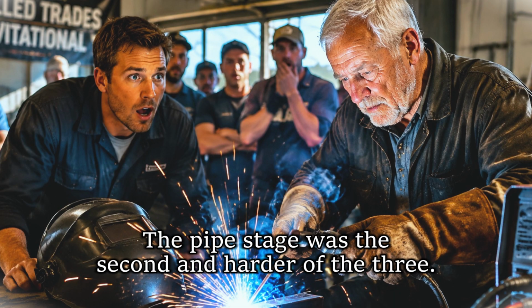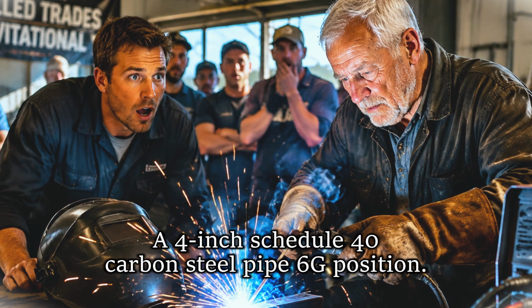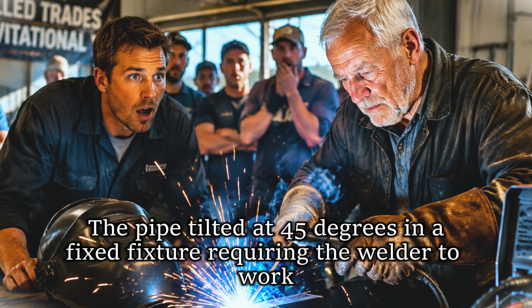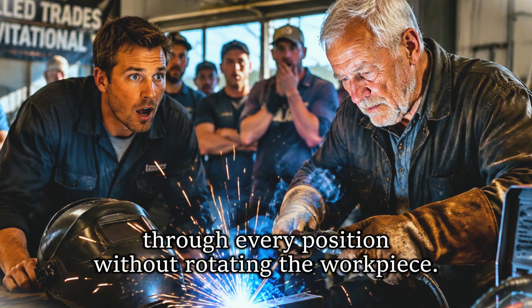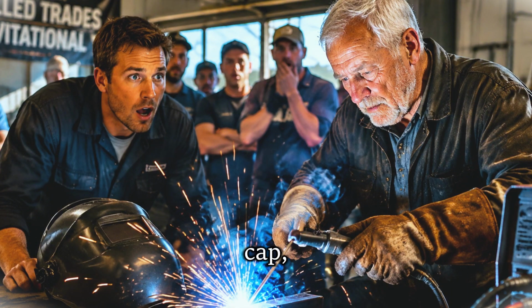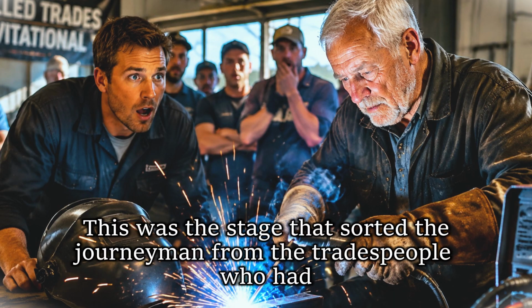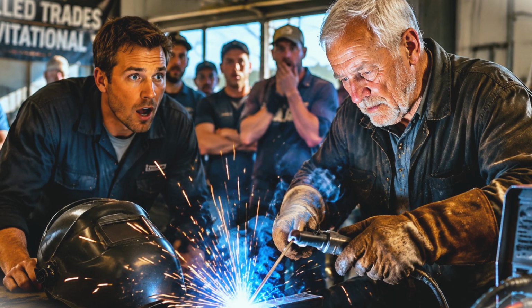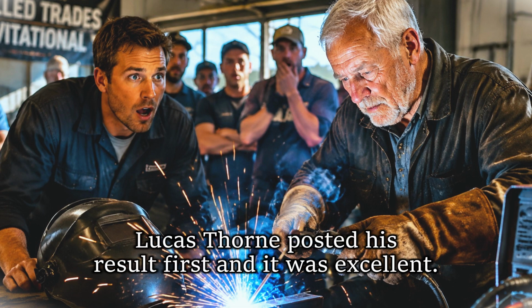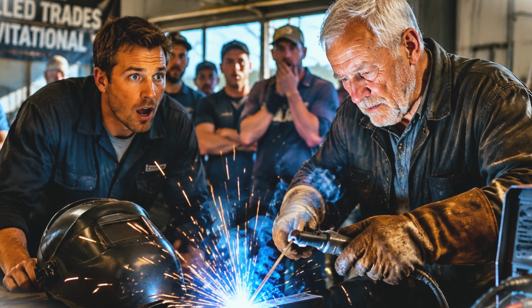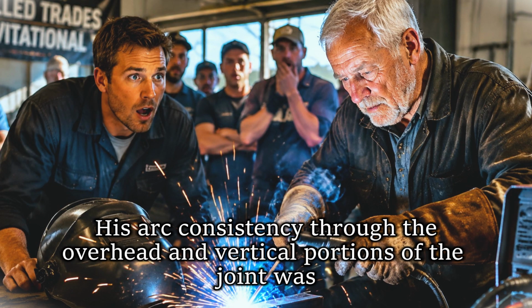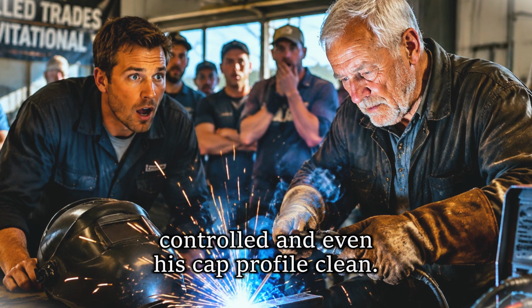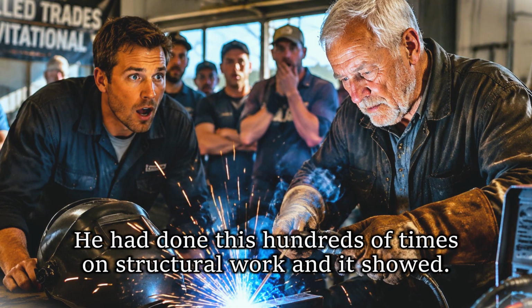The pipe stage was the second and harder of the 3. A 4-inch Schedule 40 carbon steel pipe, 6G position. The pipe tilted at 45 degrees in a fixed fixture, requiring the welder to work through every position without rotating the workpiece. Root, hot pass, fill, cap, full penetration. This was the stage that sorted the journeyman from the tradespeople who had put in the real hours. Lucas Thorne posted his result first, and it was excellent. His arc consistency through the overhead and vertical portions of the joint was controlled, and his cap profile clean. He had done this hundreds of times on structural work, and it showed.